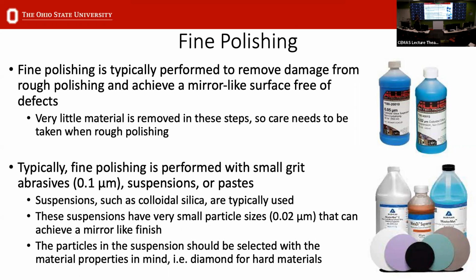So it's important to note that if you go right to this step and don't do the rough polishing, progressively moving down, you might achieve a nice mirror-like surface, but you still have several microns of damaged material that will then hinder your electron microscopy. So this is an important aspect of it, but it's typically what is useful for getting that very fine mirror polish before you go into the microscope.